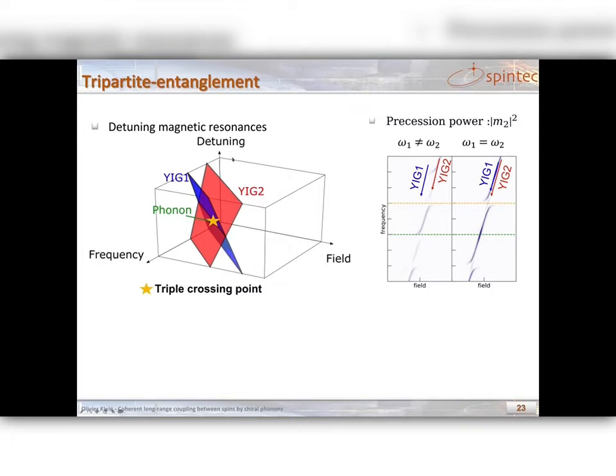So far, we had two YIG layers that are different in resonance frequency due to a slightly different nominal character. So, if we can introduce a third parameter which can detune Kittel 1 and Kittel 2, we can, at a certain point, arrive at the triple crossing point of the three resonances. So basically, we want to tune Kittel 1 and Kittel 2 to be degenerate with an acoustic resonance. And now, what do we expect?